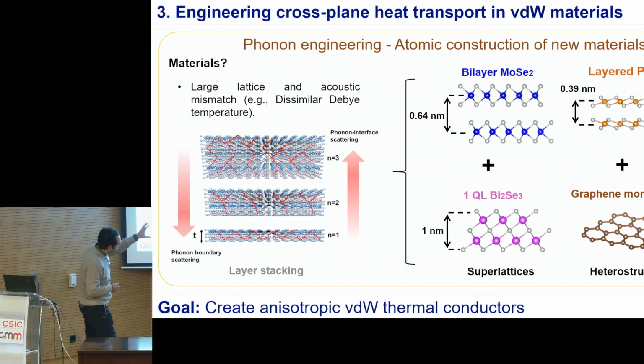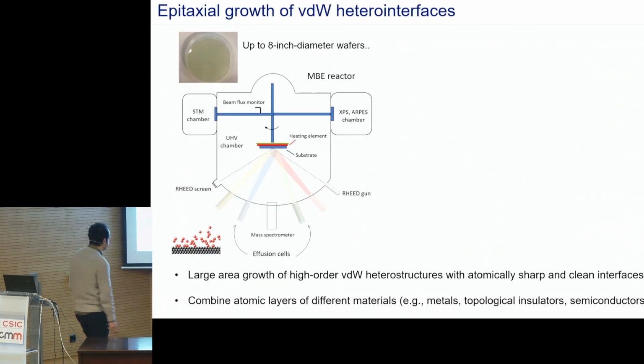So we created superlattices based on these materials, and then we also created layer stacks based on graphene monolayer and layered palladium diselenide. So why did we do this? Because this is completely the extreme scenario where we don't have any lattice mismatch. So we wanted to see the two different extreme cases.